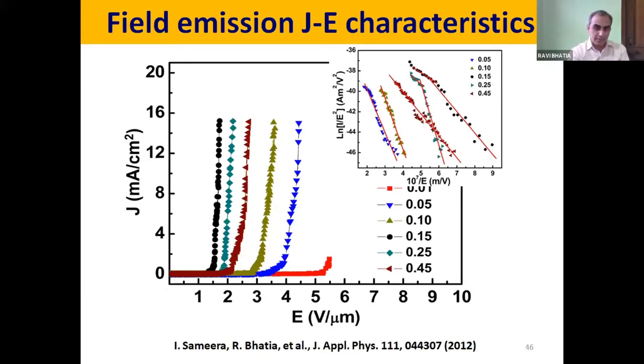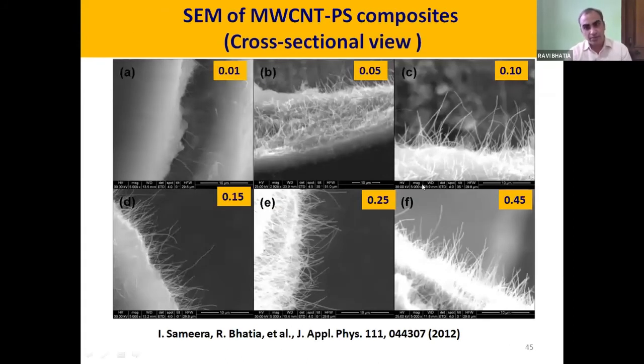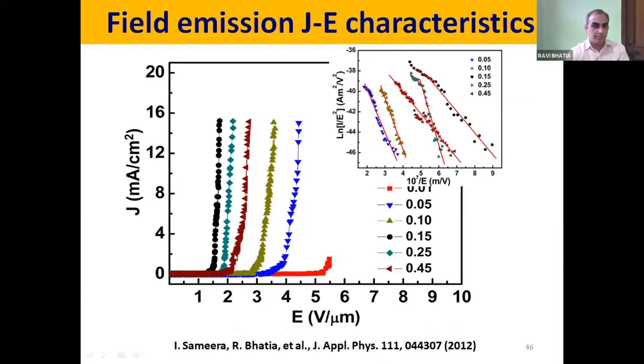At the highest loading, 45% and 25% loading, there are enough protrusions which screen out the emission of electrons. For example, here you have a large number of protrusions. Now the electric field is applied here. Because of the screening effect, which causes shorting or shunting of the currents from these particular tips, the voltage has to be higher for the emission of electrons. While in the case of the 15 weight% sample, the 15 weight% sample exhibits the lowest turn-on field, lowest threshold field, and almost the same current density from the emitted electrons.